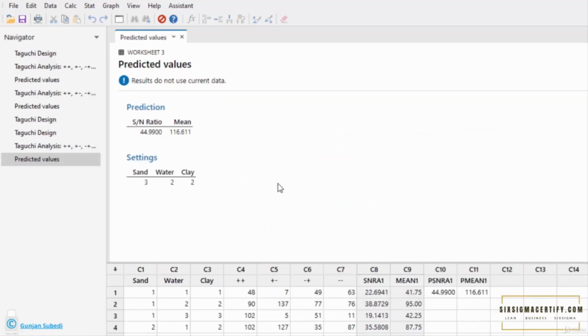So what it shows is that the maximum signal to noise ratio we can get is 44.99, and the maximum compressive strength that we can obtain while setting the sand at level 3, water at level 2 and clay at level 2 is 116.6 newton per millimeter square. That means if we set these control factors at these levels of composition, we can get the maximum compressive strength of 116.6 newton per millimeter square. So we have two pieces of information here. To diminish any effect of the uncontrollable factors, we should select the controllable factors in this composition, and the maximum compressive strength is also calculated by the Taguchi method.